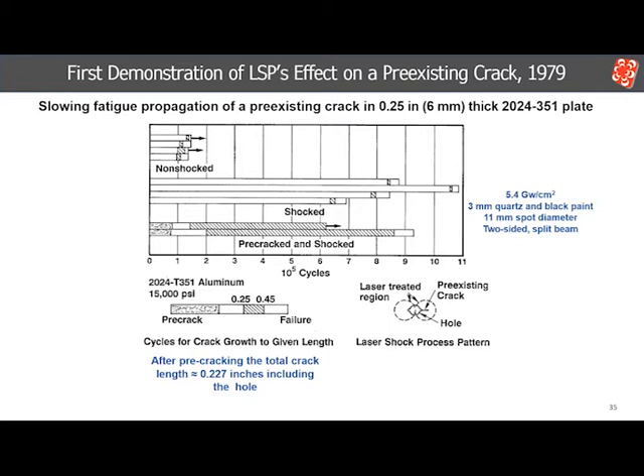In the initial unshocked condition, the fatigue life was 1.2 to 1.4 times 10 to the 5th cycles. In the first laser peen set without pre-cracking, the fatigue life was nominally increased 6 times. In the second set, laser peening after pre-cracking, the fatigue life was increased about the same amount. Although the test started with a crack present, the laser peening extended farther out in front of the crack, contributing to this increase in fatigue life.